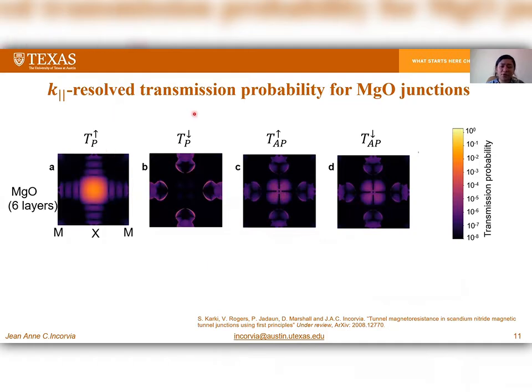Similarly, we did a k-resolved transmission probability for MgO junctions to validate our results. We saw in the parallel up channel, there is a high transmission around the gamma point, which is filtered out in the parallel down channel. And similarly, we see very low transmission in the anti-parallel channels.